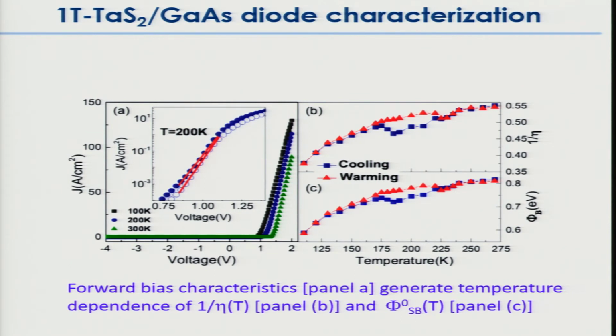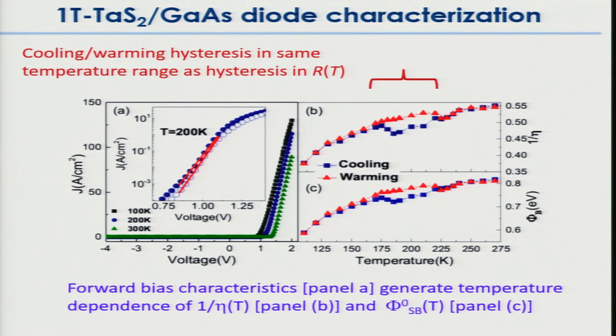And let me show you the capacitance data. So cooling and warming hysteresis is the same in temperature range as the hysteresis in R(T), and that's indicated by this bracket. So we're seeing evidence in the diode at the interface, the evidence of the CDW. Now you think of a CDW as being in bulk, but you have to terminate the resistor, the charge densities at the interface. So what we're doing is measuring the CDW in a different way. We're measuring it as it appears at the interface of this Schottky barrier. And that's what these data represent here.